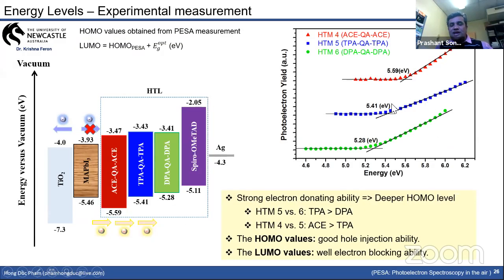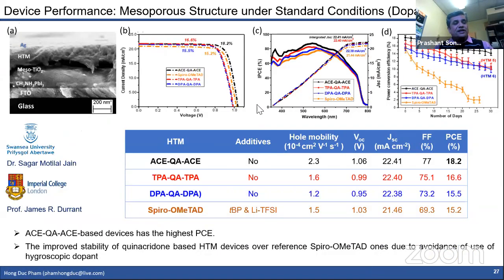And looking at these 3 compounds, again you see the HOMO values are quite low, 5.59. Usually if HOMO values are 5.1 or maybe 4.9, they are not good because they may have a high ability to oxidize because of the very high HOMO. We got a very low HOMO. That is really one of the striking features of these new HTMs, how we can get a stable performance. And they also match well with the standard perovskite HOMO value of 5.46, and again it has LUMO values that are not that close to the LUMO of standard perovskite.